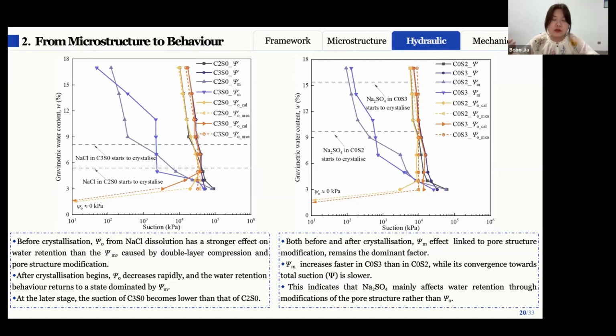And if we look at the right figure about sodium sulfate, a different behavior occurs, because both before and after crystallization, the matric suction plays a dominant role. The fast increase of matric suction in S3 compared to S2, together with its slower convergence towards the total suction, suggests that sodium sulfate crystallization significantly modifies the pore structure and affects the water redistribution.